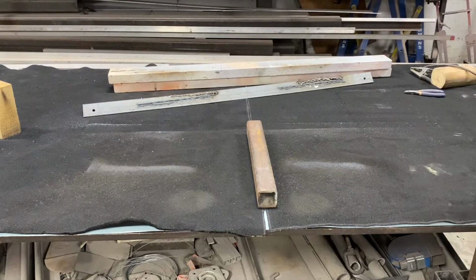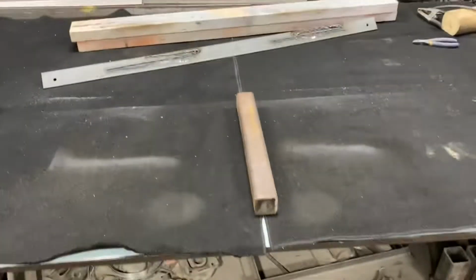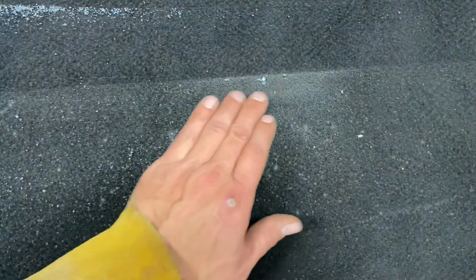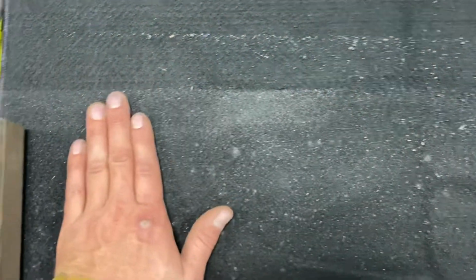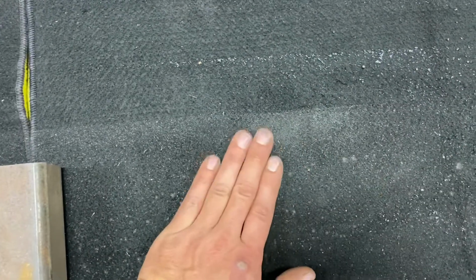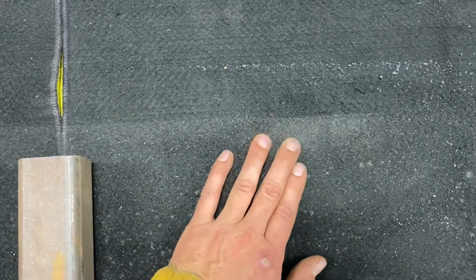This is another thing I do not like about the standard blankets. As you can see, right here, where the heavy grinding is, it just starts melting in. And it just starts burning away that carbon felt. The 3 layer one, it still melts in, but it's not near as bad. I mean, this right here, even if we grind on the same spot, is gonna last longer than the standard one.